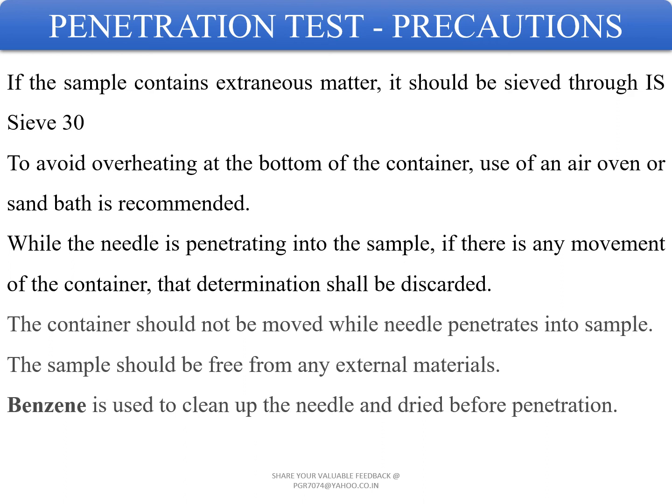Benzene is used to clean the needle, which is dried before penetration, because if there is any extra material sticking to the penetration needle, then it will generate a resistance as the needle penetrates through the bituminous sample, and the results reflected will be erroneous in nature.